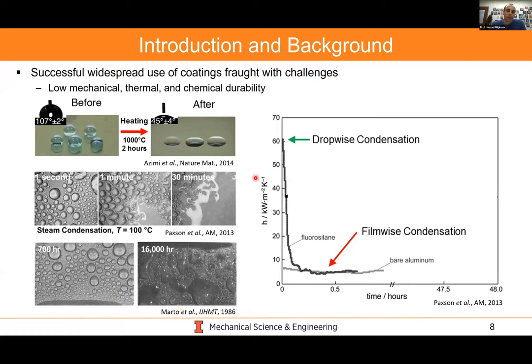In terms of the heat transfer coefficient, you can see here in the plot on the right, you start out fantastic, 60 kilowatts per meter squared Kelvin. And then within hours, you're down to the performance of bare aluminum, which is not where you want to be. And this shows you the main challenge to this problem, in that very thin films are very hard to make durable enough to sustain dropwise condensation for a long time. This has been known for the past 5-6 decades.